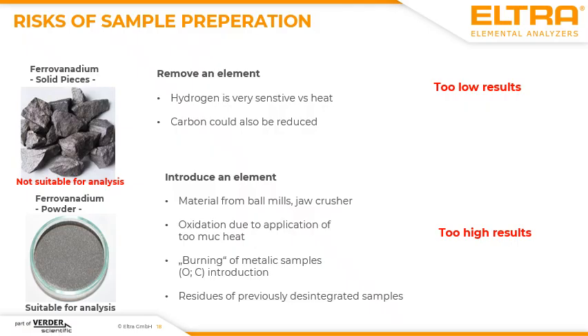Sometimes the samples have to be prepared as powder because otherwise they cannot be analyzed. When you have a look at the picture of the solid ferrovanadium, these kinds of big pieces are not suitable for carbon, sulfur, or oxygen, nitrogen and hydrogen analysis because they are just too big. Then you usually can use analytical ball mills, for example, to prepare a sample, or other analytical techniques to get a suitable sample size which can be applied to the furnace of the analyzer.